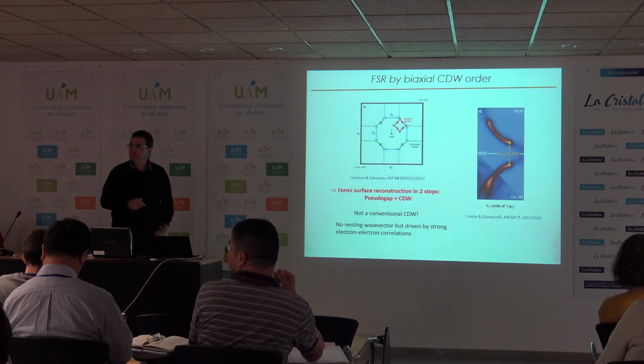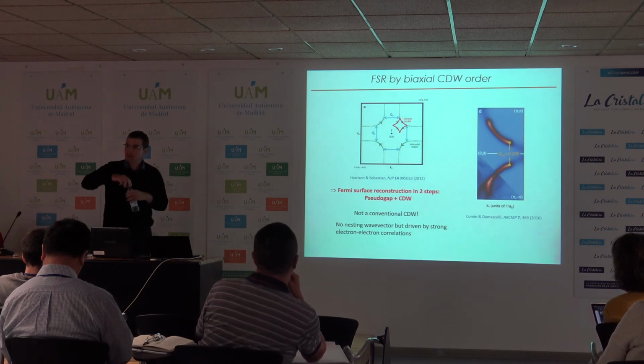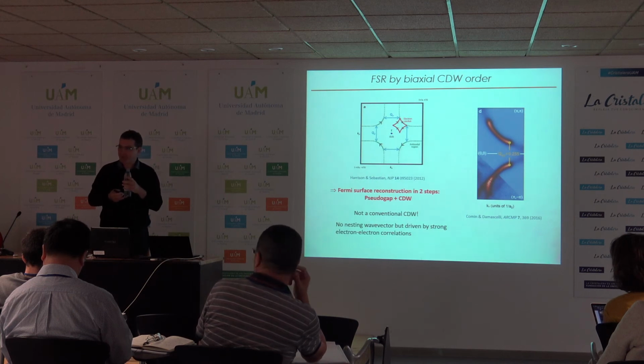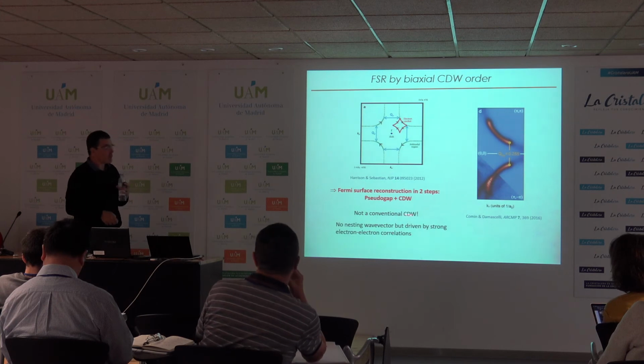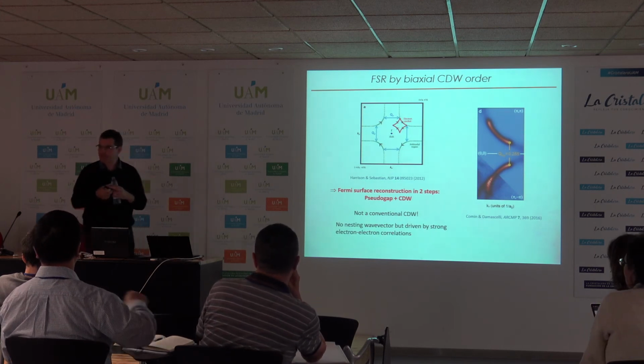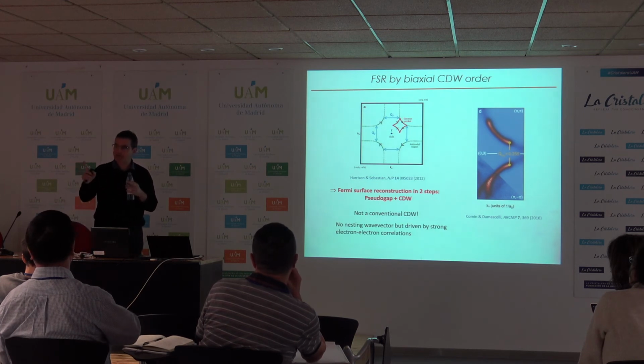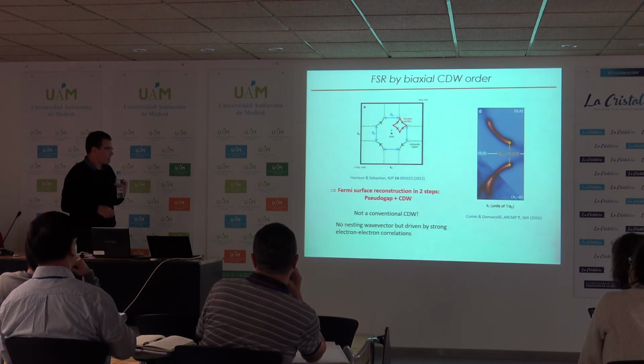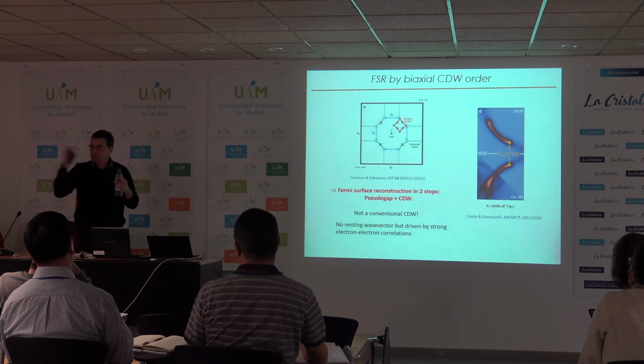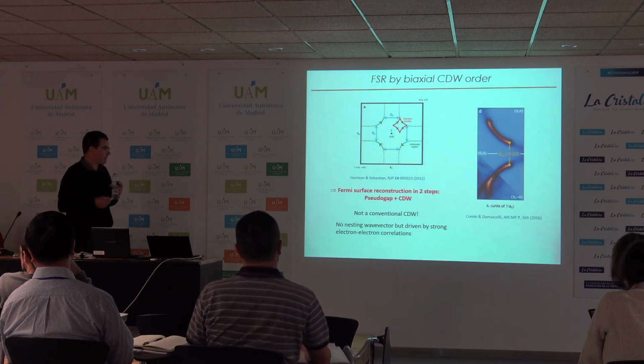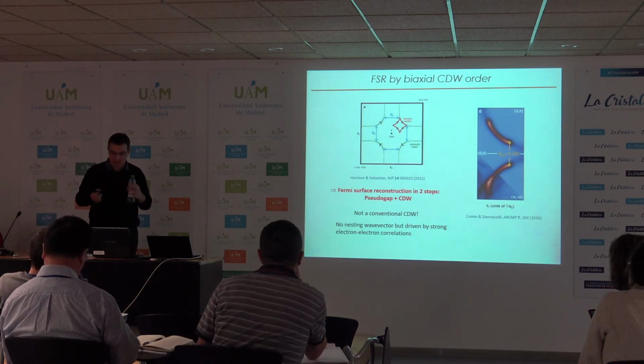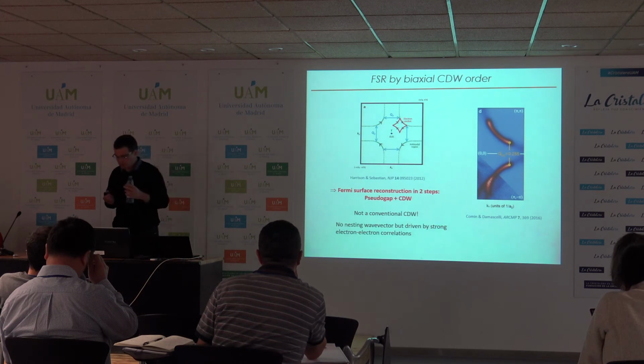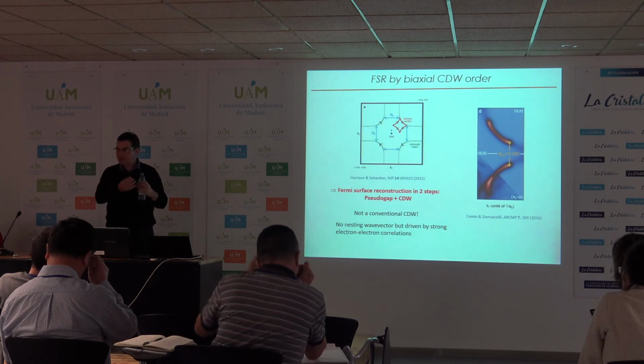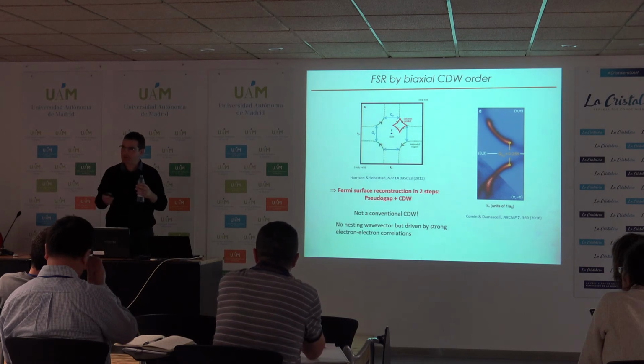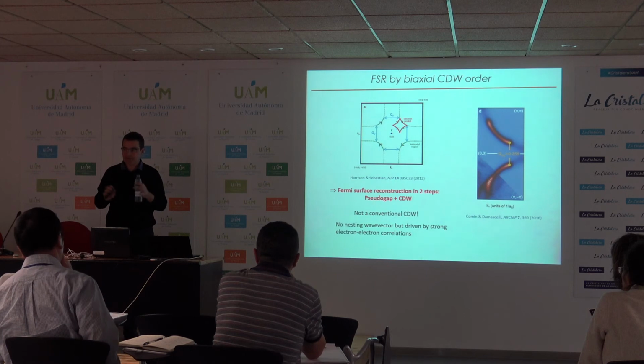Question. So where does the gap of the CDW open? Actually, this is a good question because, as I put here, this is not a conventional CDW where you see clearly a gap. But it has been seen recently by Raman scattering. And this is not a conventional nesting charge density wave. It's certainly driven by strong electron correlation. As far as I know, we heard in your talk that you are pushing to prove that this is not a conventional charge density wave, but a pair density wave state. But for the moment, there is no convincing evidence in YBCO, but this is okay.